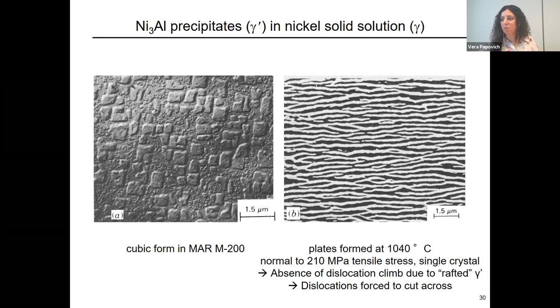And another example of what can happen at high temperature and with application of stress is that a kind of rafting structure is formed. So when the nickel-based alloy, this is a single crystal, so this is not a polycrystal or equiaxed material, a single crystal alloy, the temperature is up to 1,000 and a certain tensile stress is applied in a single crystal. So what happens with these gamma primes, they form a rafting structure. Yeah, they form this kind of elongated plate-like structure.